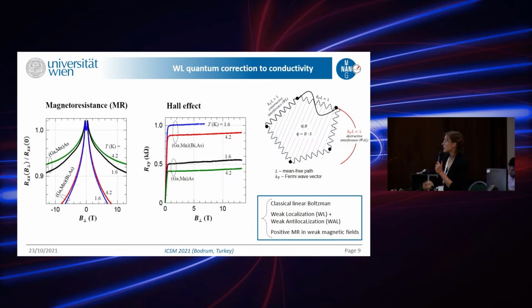And then in magnetoresistance, we actually have a combination of 3 interesting phenomena. In the lower fields, below 0.4 Tesla, I would guess, we do have our positive magnetoresistance, so this reorientation. Then we have the combination of weak localization and weak anti-localization. And then if we reach strong enough fields, we didn't, but we will probably observe the classical linear Boltzmann behavior.